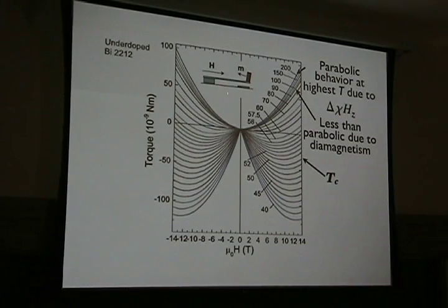totally non-magnetic or paramagnetic. Then as soon as you go below a certain temperature, the susceptibility drops. It becomes less than quadratic here, less than parabolic, sorry. And then it keeps dropping, and it becomes completely diamagnetic. Well, this is already in the superconducting state, but long before superconductivity, this effect occurs. So it's also a signature that perhaps in the pseudogap there are little regions of superconductivity, but it's not the whole sample. Only at TC does the whole sample come in.